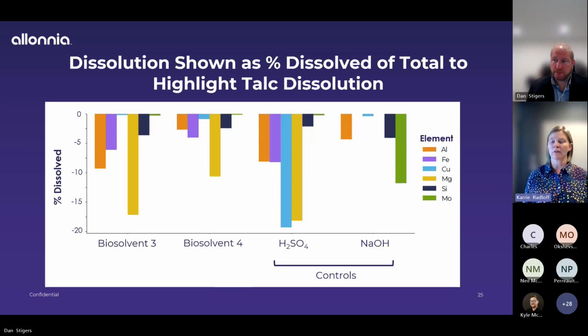Okay. We've also looked at other concentrates. So this is an example of a copper con, where we were looking at screening it against our library of biosolvents. Again, I'm showing 2 examples here. Here we're really focused on removing silicates, specifically magnesium-bearing silicates. So we're trying to get increased amounts of the magnesium and the silica out, and that's the yellow and blue bars. And if we look at our controls, typical ways you could do this with an acid leach or a base leach, particularly with sulfuric acid, you can remove a lot of the magnesium, but you're also going to remove a lot of the copper with it.